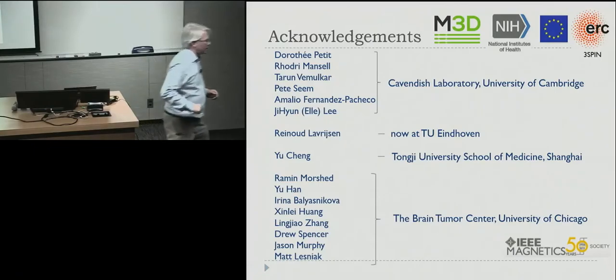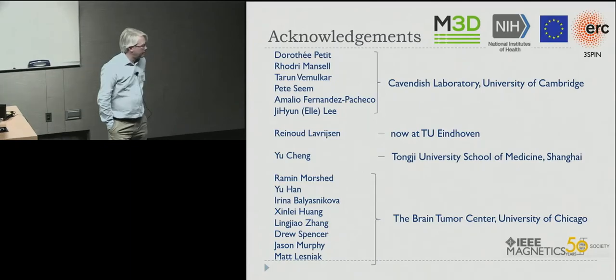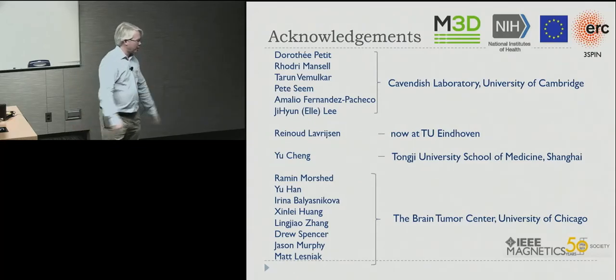Randy, do you have a question? Yeah. I was going to comment on what John Payne said before, which is that the thing about those cobalt platinum is that they actually switch in a very different way than normal, because the cobalt layers switch layer by layer, owing to thermal fluctuations at sharp corners or defects or whatever. And so even if it's like a 30 nanometer sample, you still have this problem that you get domain wall nucleation across the side of it, and you actually have to get the size down very small before that quits, to 10 nanometers. So it's almost a two-dimensional material. I agree, absolutely. It's very, very abnormal. And wonderful.